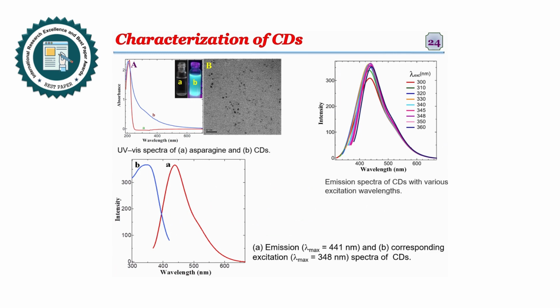So, as we discussed earlier, luminescence is an important property. Figure A is the L-asparagine and B is the NCDs. A does not show any luminescence, and B exhibited blue luminescence under UV light. Similarly, in the UV-visible spectra, asparagine does not show any band, and the NCDs exhibited a shoulder peak around 340 nanometers, corresponding to the formation of NCDs, and the spherical dots indicate the formation of carbon dots, which is obtained from the HRTEM analysis. And the carbon dots exhibited excitation-independent emission, and the emission is observed around 441 nanometers with an intensity of 400.